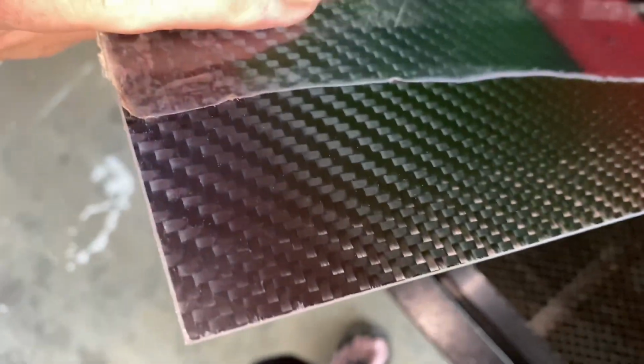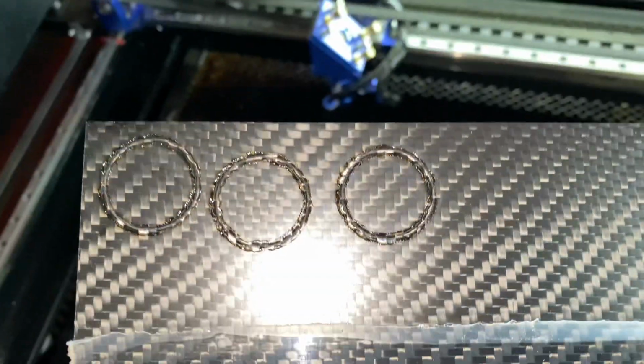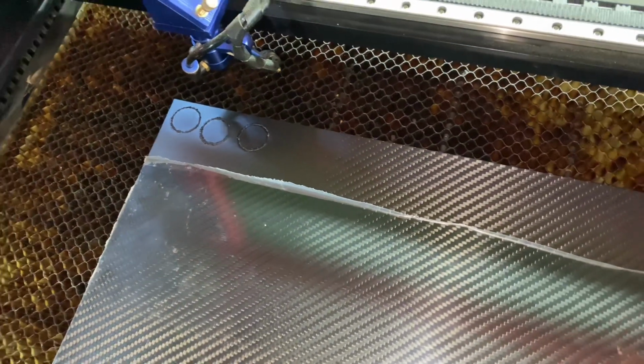Quite bright when it's cutting too. Alright, so that didn't look like it went through either. So it's 70% power. Yeah, I mean, that's pretty nasty, isn't it? Yeah, no chance. It's definitely not going through there. It doesn't even look like it really cut that much deeper than the first two. But anyway, I'm going to go with a negative as far as cutting the carbon fiber goes on this machine.